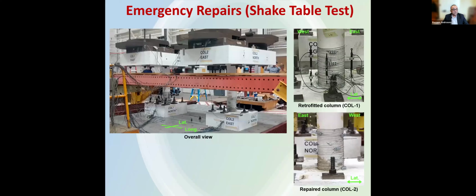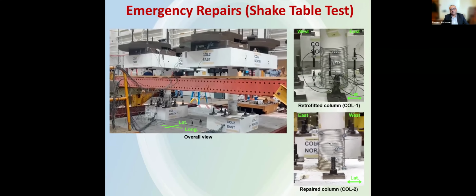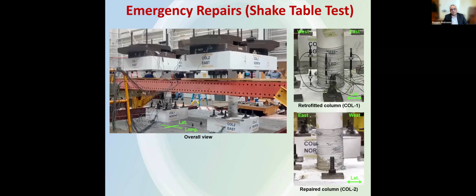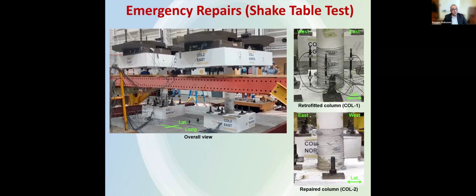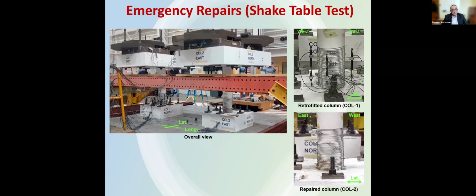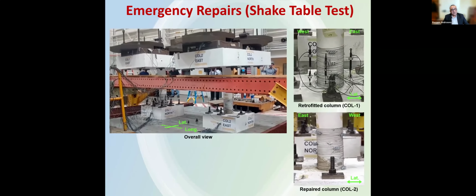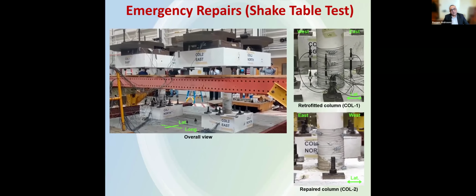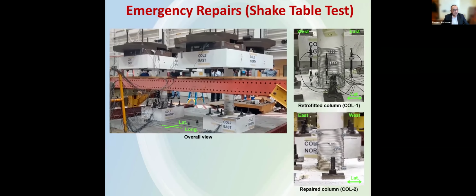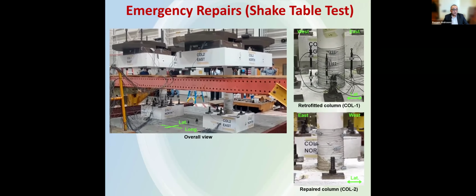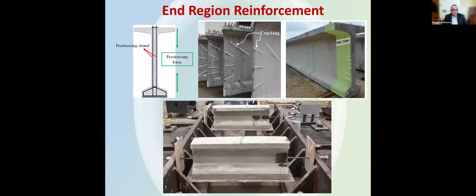And we subjected both columns to a bi-directional record from the Loma Prieta earthquake. And I want you to watch here how both columns behave together. You will notice here that both columns were behaving almost identical. The capacity of the damaged column was restored. Its ductility was improved significantly just with 2 millimeter wires in a matter of 2.5 hours repair. So definitely that was a great successful test here, showing the potential of these materials for active confinement.